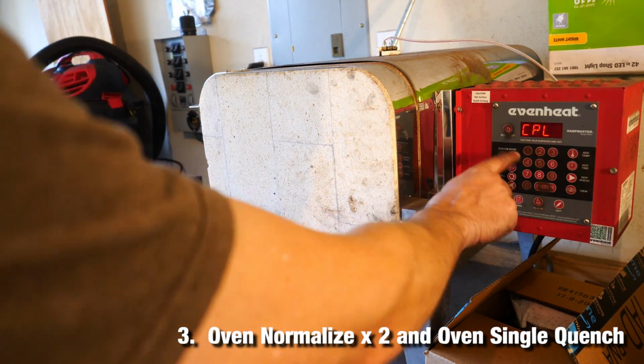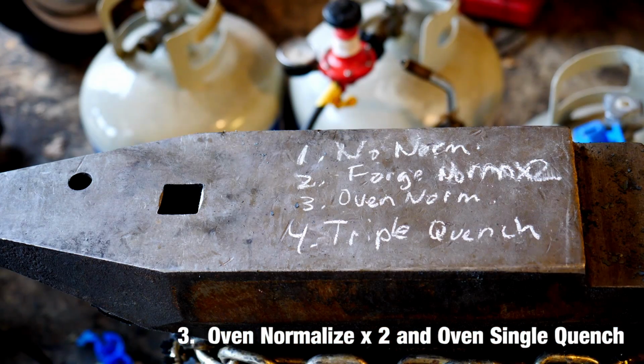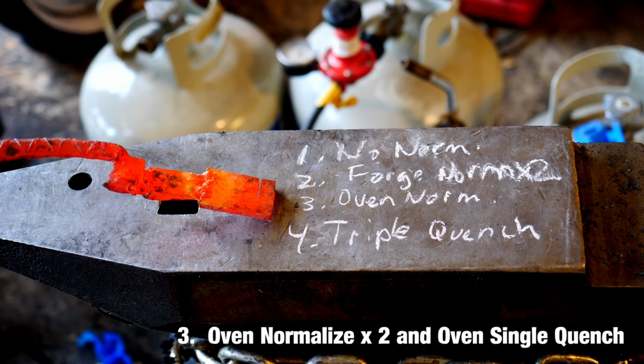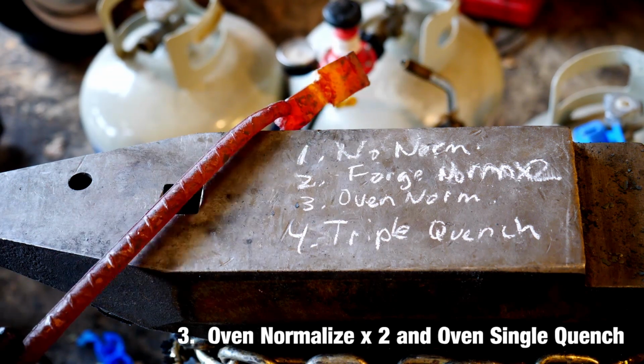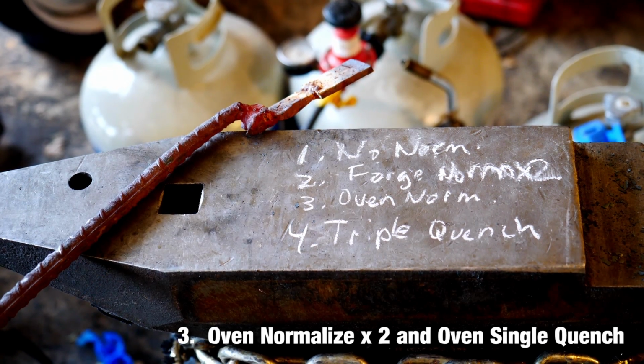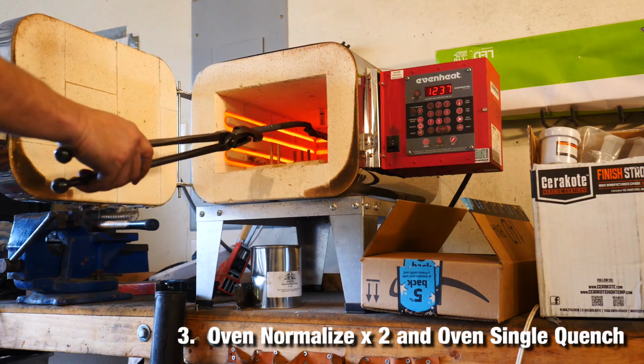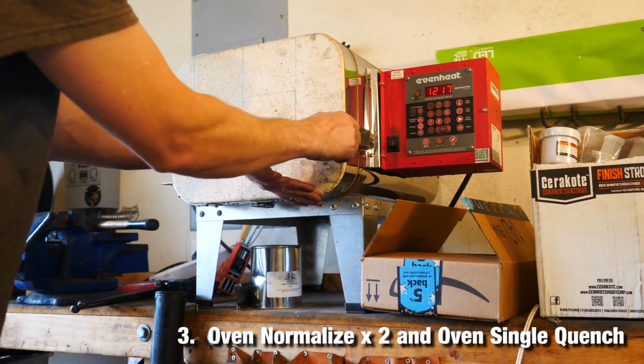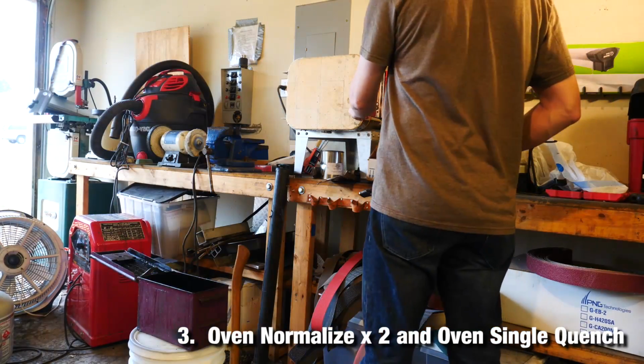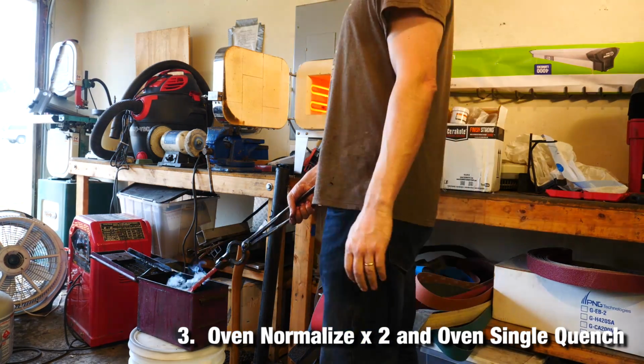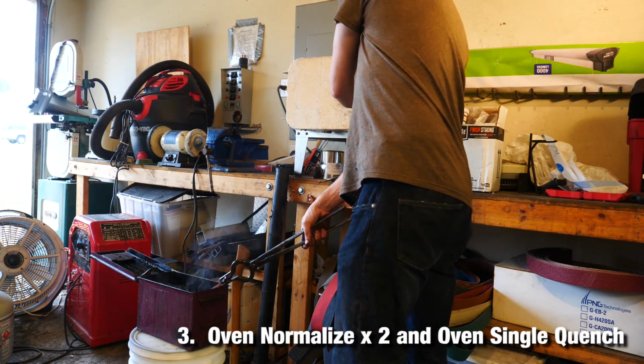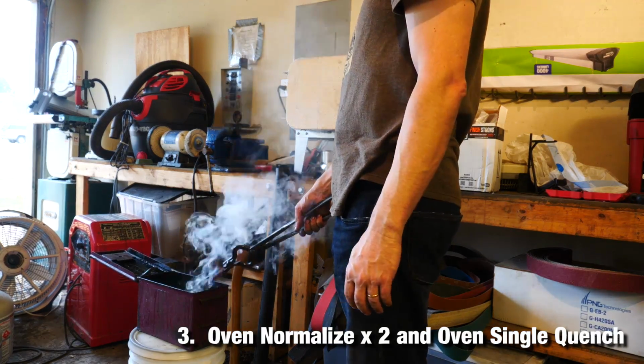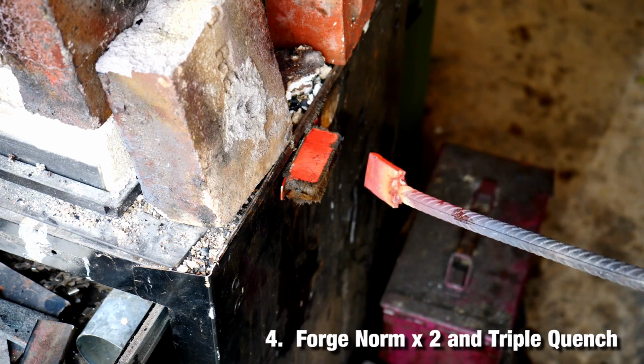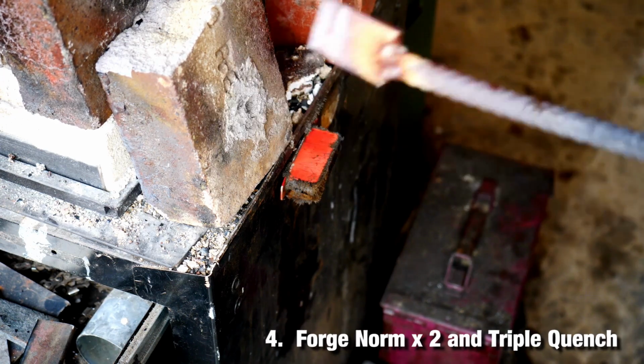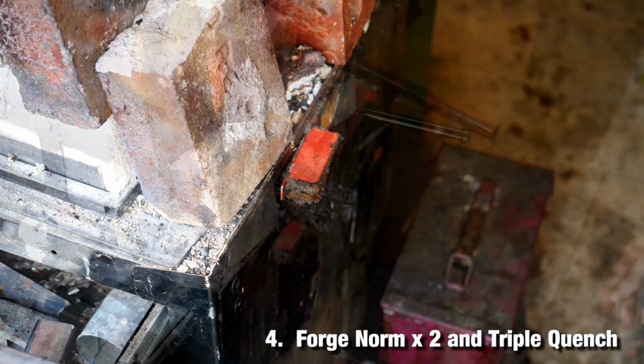Number 3, now we're going to normalize it twice. First at 1600 degrees, then at 1550 degrees, then quench in oil again from 1525 degrees Fahrenheit. Now for our ultimate forgeside quench routine, 2 normalization cycles followed by the triple quench.